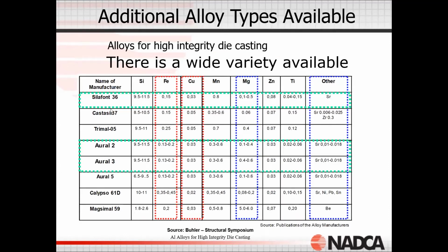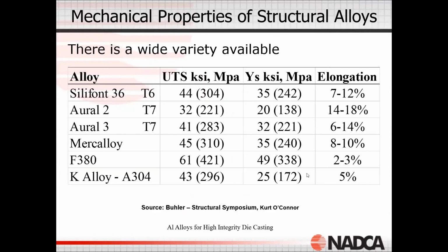So these are some of the alloys that I mentioned just a few minutes ago in some of those applications: Silifont 36, Castasil 37, Aural 2, Aural 3, Aural 5. So we can see these alloys all have that silicon range anywhere from 7% all the way up to about 11 or 12%. They're controlling the iron and the manganese, very low iron levels, 0.15, 0.25, 0.13. Controlling the manganese levels, very low copper. I mentioned that these have great corrosion resistance because we're limiting the amount of copper in these alloys, adding in magnesium for strengthening, and then modifiers like strontium to help modify the alloy to give us good fluidity while we're filling those castings.